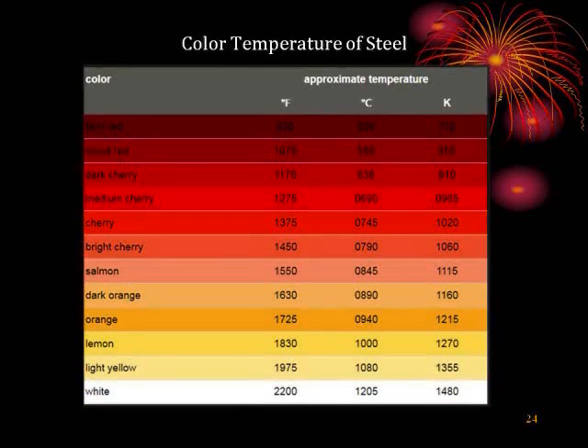Blacksmiths usually use the color of the steel to tell whether it's hot enough to start working on the steel. And the color, most important one, is the cherry color, which is about 745. Then salmon is about 845, and lemon is about 1000, and white is about 1205. Even when this thing becomes white, it is still about 300 degrees C below the melting point.